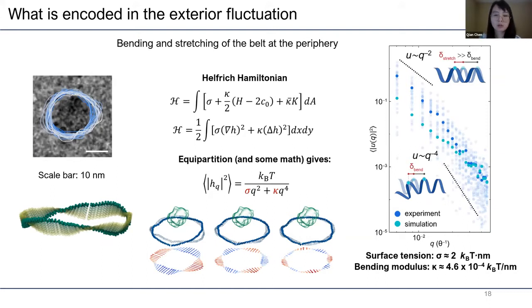There are three pieces of information I hope to highlight here. The first is, as we overlay the data from MD simulation with our experiment, they overlap decently well with each other, highlighting that the fluctuation is generic. Second, sometimes the fluctuation falls into this bending dominant region with a -4 power law in this high Q region, with small length scale due to intermolecular interaction. And then you can also fall into this stretch dominant region with a -2 power law, corresponding to this low Q region with large length scale, corresponding to large surface tension. And lastly, from fitting these two curves, we can back out the surface tension and the bending modulus, all from these real space movies.